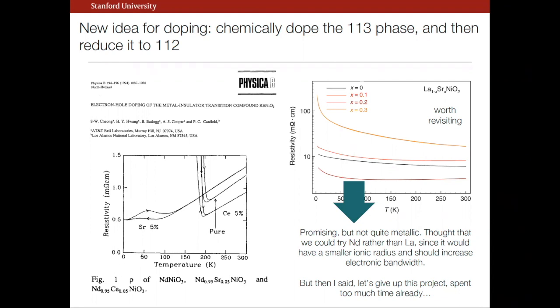And what was interesting was that fairly slight doping could drastically move this around, and actually by 5 to 7% strontium doping, you can completely suppress this. So that was the idea, and this was a first scan using the lanthanum version of the nickelate. So this is now the reduced form. And you can kind of see what's happening here. So at nominal different strontium doping levels, you can see that this guy gets fairly low. So resistivities of a few milliohm centimeters, it looks like it's close to becoming metallic and interesting, but not quite there.